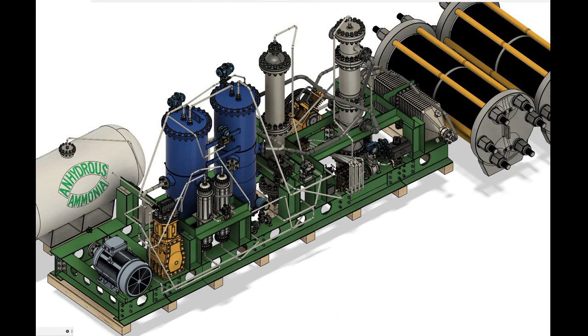While carbon monoxide is not classified as a permanent catalyst poison, it poses a tremendous challenge upon designers. Synthesis gas from methane reforming contains trace amounts of carbon monoxide even after passing through the water-gas shift reactor, requiring an additional methanation reactor to remove these residual impurities. In China, where coal is a primary hydrogen feedstock for ammonia synthesis due to the lack of natural gas, short catalyst lifespan has been a common feature for many medium-size ammonia plants. If subjected to even trace concentrations of sulfur, the iron catalyst will rapidly deactivate.